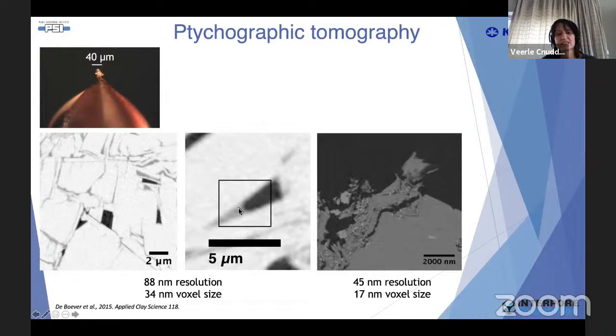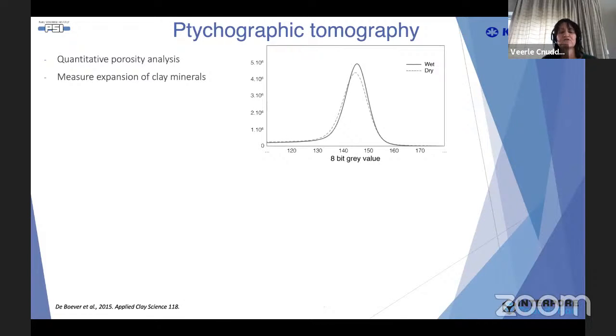We could even see liquids inside the pore structure and try to determine the contact angle. We could quantify the porosity, and we could also measure expansion of clay minerals because the technique is non-destructive.